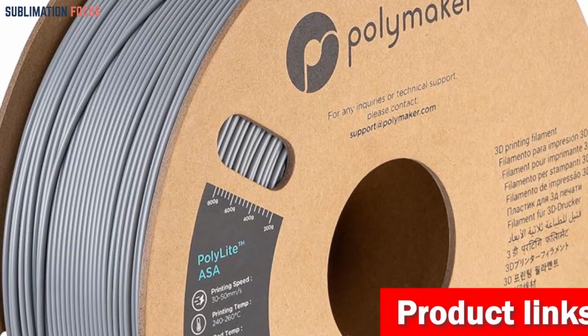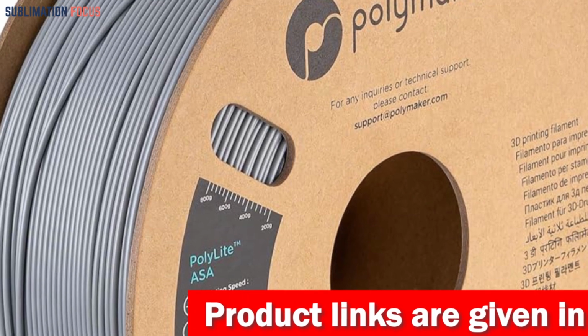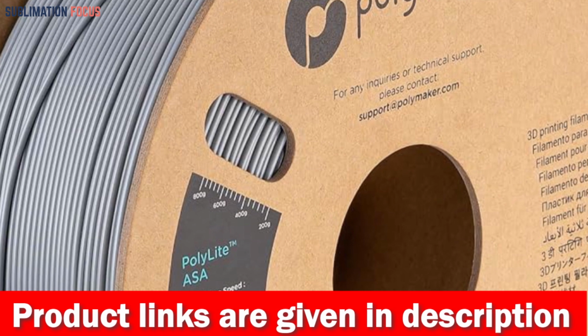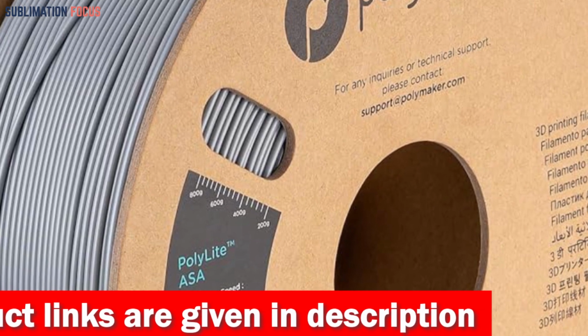In terms of printing settings, Polymaker ASA provides recommended parameters to achieve optimal results. These include a nozzle temperature of 250 degrees Celsius, a bed temperature of 90 degrees Celsius, and a print speed of 50 mm per second.